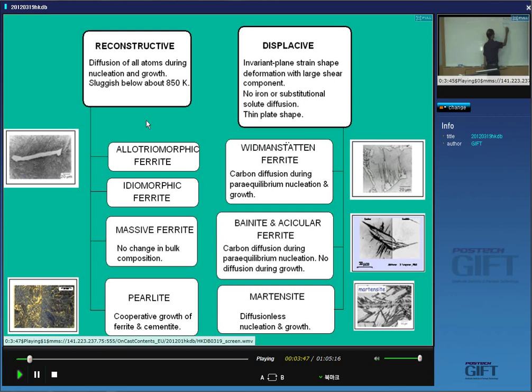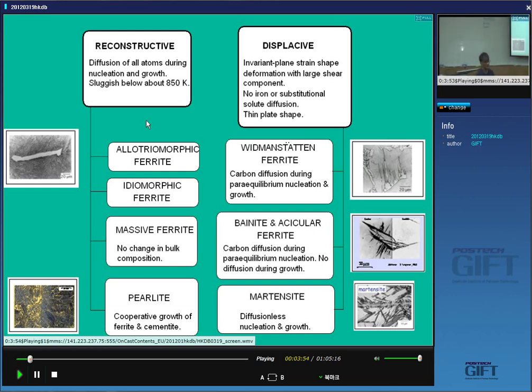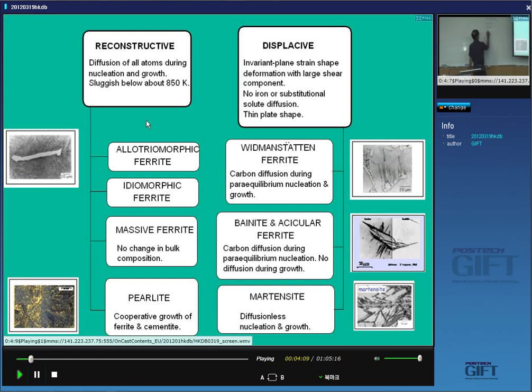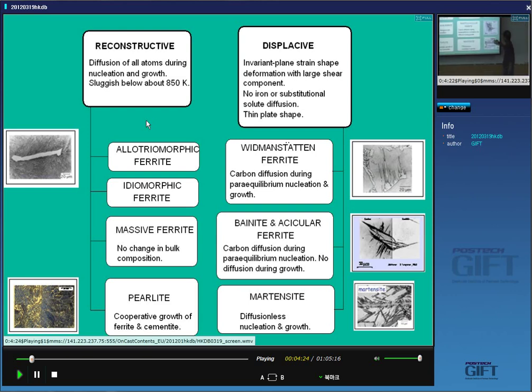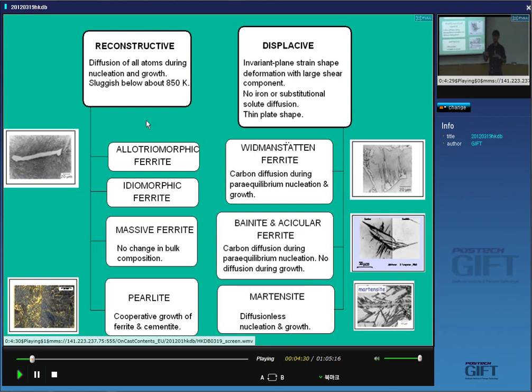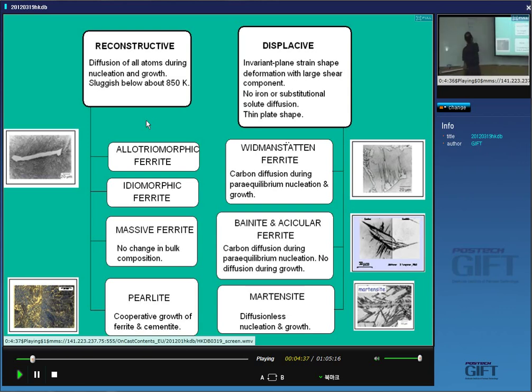Hard. What else? These are physical properties of martensite. Diffusionless. There is a clear crystallography — the plates are not forming on random planes. They are forming on particular planes and with a particular orientation relationship with respect to the austenite. So there is a strong crystallographic element to martensite.